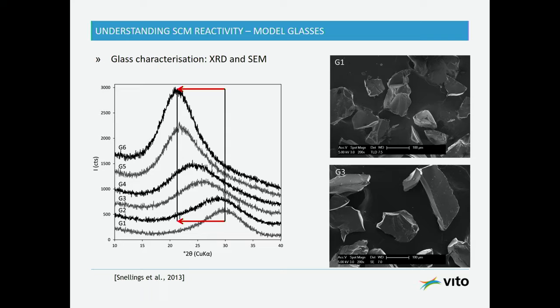So we synthesized these glasses in a lab furnace, and these are the XRDs, so they are quite homogeneous. We ground them, and we have these small pieces. They are actually a bit larger than what you would actually use in blended cements, but this is to do our dissolution experiments in very dilute solutions afterwards in a better way, so we can follow the buildup of ions in the solution over a longer period without having any precipitation of hydrates.